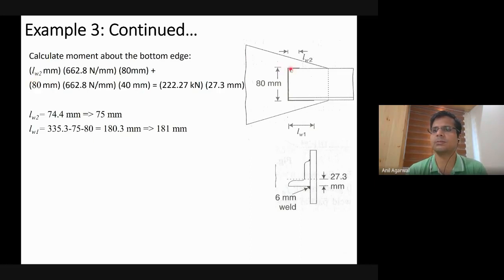So LW2, that is the length, multiplied by the strength per unit length will be the total force of this weld. 662.8 is the strength per unit length, multiplied by the length gives me the total force of this portion of the weld, multiplied by the distance from here, that is 80 millimeters. That gives me the moment coming from this weld's failure. At the same time, if you consider this weld, its centroid is somewhere here. So this length multiplied by the strength per unit length gives me the total force, multiplied by 40. So there will be a moment equal to this much. These two moments from the weld have to balance the total moment coming from the external load, which is 222.27, the design strength of the angle, multiplied by the distance from this edge, that is 27.3. And I can solve this equation. This is a single equation with a single unknown, LW2. So LW2 turns out to be 74.4. I approximate that to 75.